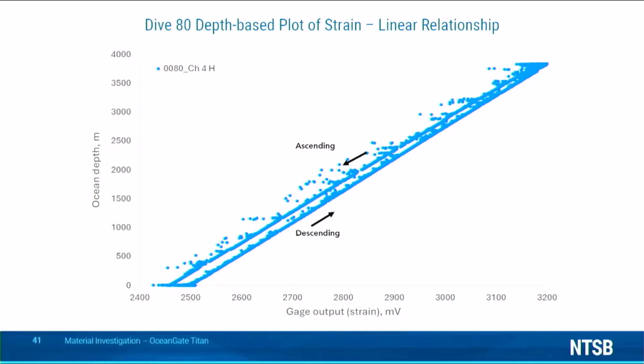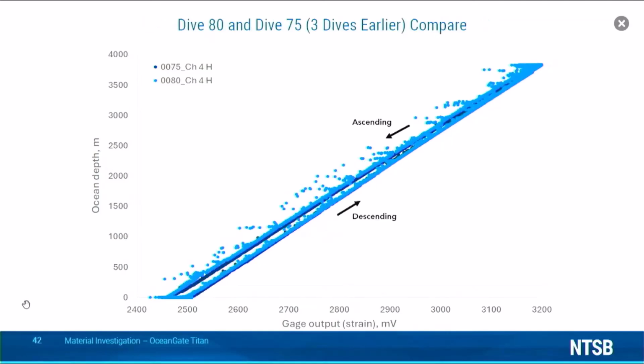Plotting the data in this manner is more akin to a stress strain plot, which is a standard way of visualizing this type of data. For dive 80, prior to the event, the relationship between strain and dive depth was a straight line for both the descent and the ascent. Going backwards in time by 3 dives and comparing dive 80 to an earlier dive 75 reveals no significant change from dive to dive.